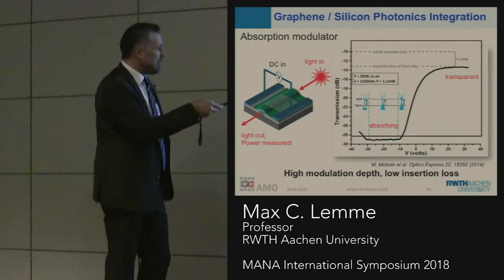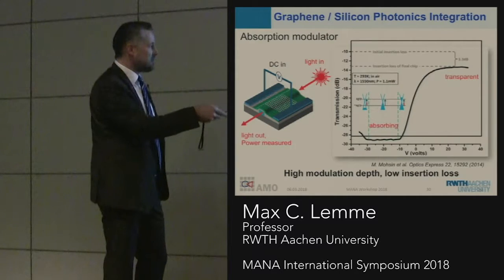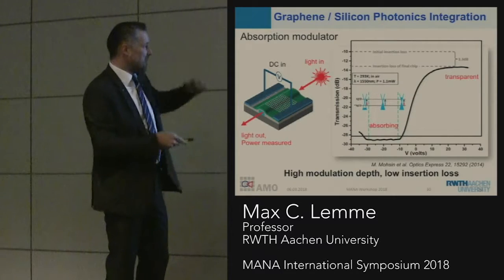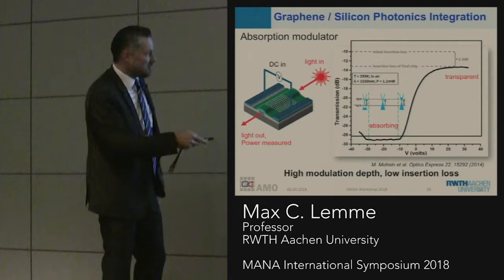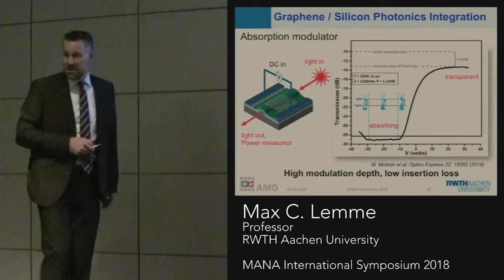If we apply more than minus 10 volts to the top graphene, we tune the Fermi level in the lower graphene, and we absorb the light here.